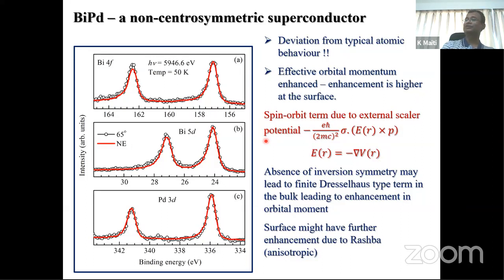Okay, so one thing is from the core level spectrum, it's very clear that in the bulk, the bismuth core level effective orbital moment is enhanced due to the orbital moment coming from this lack of inversion symmetry. Okay, and this effect becomes even stronger. Now you know that in the bulk, if you have this absence of inversion symmetry, you can get this Dresselhaus kind of term in your spin orbit coupling, and at the surface, because of the translational symmetry breaking, you have this Rashba kind of effect, which also might be enhanced if you have lack of inversion symmetry even in the bulk. And that probably is giving you an additional effect on the orbital. So let's keep this in mind when we discuss the next part.